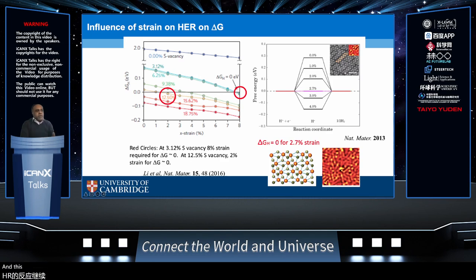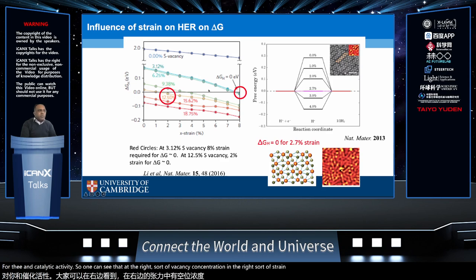thermoneutral condition that we desire for the HER reaction to proceed. And this was verified by the group from Stanford, where they plotted the delta G as a function of strain at different sulfur vacancy concentrations. I showed you in the previous slide that it's the sulfur vacancies, that is the exposure of the molybdenum ion, that is responsible for the catalytic activity. So one can see that at the right vacancy concentration and the right strain, you can achieve thermoneutral conditions.